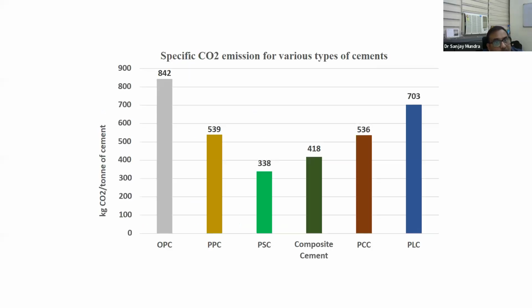This is the specific CO2 emission for various types of cement. You see in OPC, the left side you can see 842 kg CO2 per ton of cement, while you see the PPC, PSC, composite cement, PCC and PLC is very less. But if you see the composite cement and PSC, the carbon emission is very, very less. You say 338 and 418. So how can you make multiple blends? You can reduce more CO2 emission from the different cements.